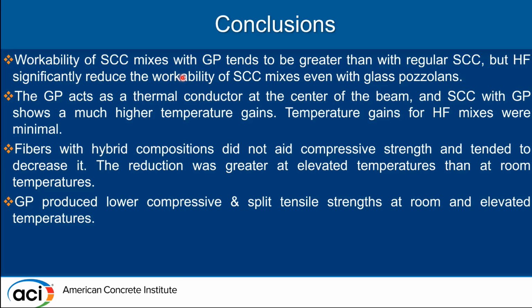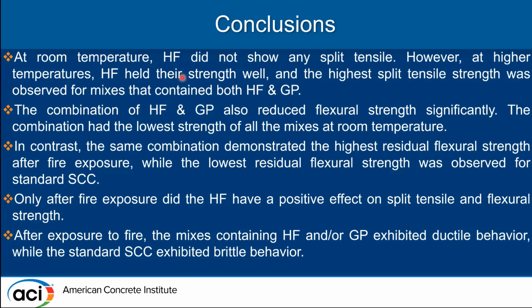Glass pozzolan produced lower compressive and split tensile strengths, both at room and elevated temperatures. However, with the addition of hybrid fibers after fire exposure, higher splitting tensile strength is observed for both HF and GP, that's the hybrid fibers and glass pozzolan. In terms of flexural strength, again, initially the highest was for the SCC, but with the introduction of hybrid fibers, the maximum was observed for hybrid fiber and glass pozzolan, and that was almost thrice the regular SCC residual strength.